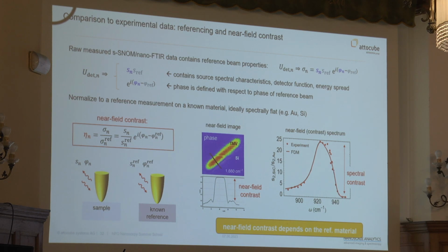If you do the measurements on silicon, that's one value. If you do it on calcium fluoride, it will be a different ratio. You have to keep it in mind. So you have to make sure that you know what the reference is, and when you calculate, you take the dielectric function for the reference there for the calculation.